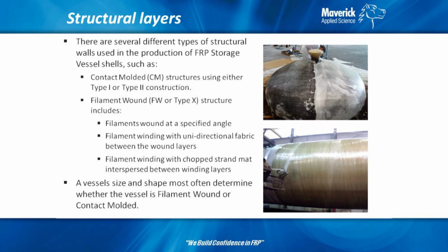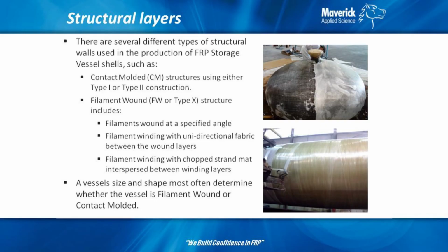Okay. So, different ways you can build things now. Contact molded or filament winding. Both have their strengths, both have their weaknesses. Contact molding of a laminate is typically going to be either a type 1 or a type 2. Type 1 is only going to have chop strand mat. Type 2 will have some kind of a directional reinforcement: woven roving, unidirectional. I think officially if you use type 2 it has to be woven roving per RTP-1. But a type 2 structure has a different makeup of the laminate package. And then type X or filament wound structures, you see down here.